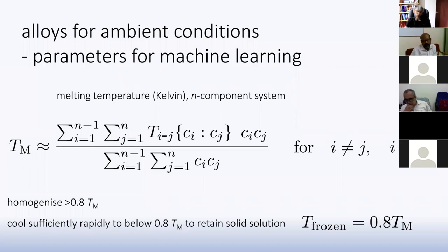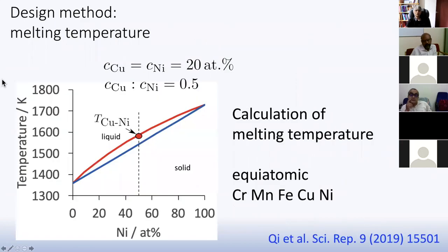Now, there are very few actual measurements of the melting temperature of high entropy alloys, but I found one in the literature, so I'm going to do the calculation for that particular case. This one contains copper actually, so it's not the normal Cantor alloy, but it's chromium, manganese, iron, copper, nickel. So I looked up the binary phase diagrams. And of course, this is equiatomic, so there's 20 atomic percent of copper and 20 atomic percent of nickel.